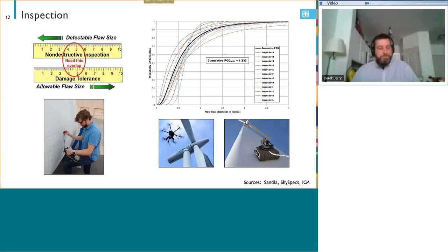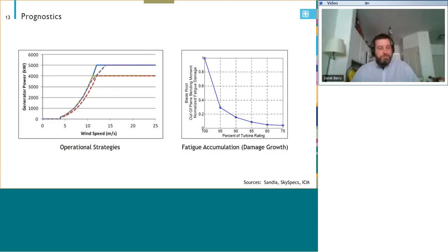In this case, we found that an inspector in the wind industry, based on what we did, was able to detect a flaw of about 1.3 inches in diameter. And so going back to the design part, if you can't catch a flaw smaller than that, then you need to assume that it exists.